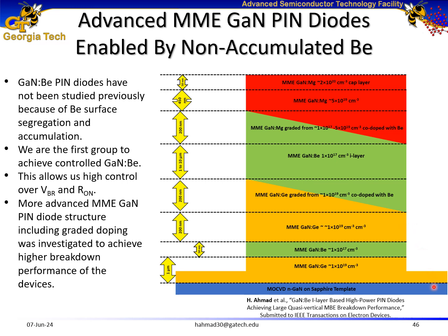Then I grew these gallium nitride pin diodes. This slide shows a layer structure diagram of my devices, where first I sandwiched a beryllium-doped gallium nitride film inside the n-type layer, and the beryllium doping was 1 times 10 to the power of 17 per centimeter cube. And then I grew beryllium-doped gallium nitride I layers with I layer thicknesses of 1, 2, 5, and 10 micrometers. And I kept the transition layer between the n-type and the I layer to be a graded junction for improved breakdown performance. Later, I deposited a magnesium-doped gallium nitride top layer with a cap layer as well. And once again, I kept the transition from the I layer to the p-type layer graded for improved breakdown performance.